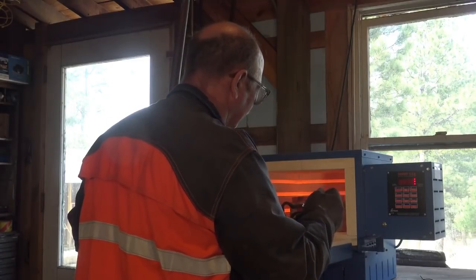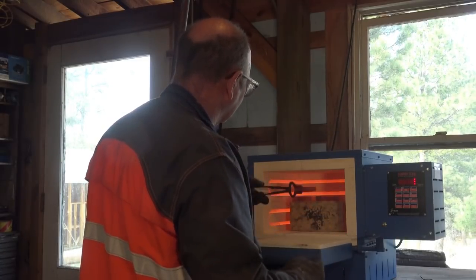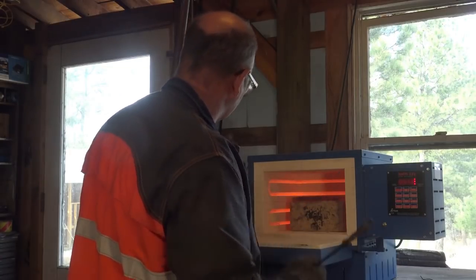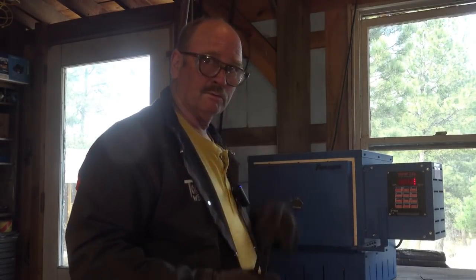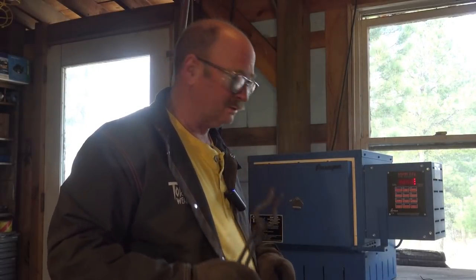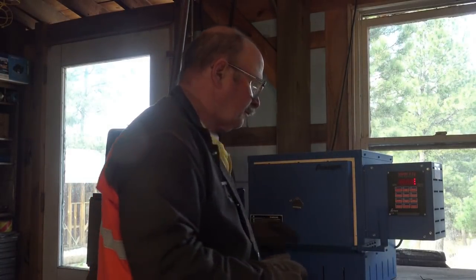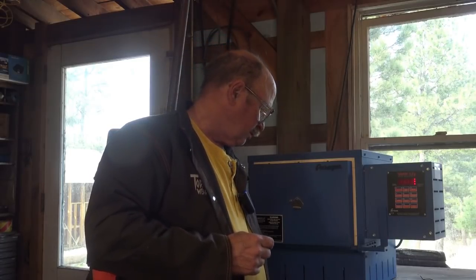It depends on where you test it. The part that's sitting up on this brick must still be a little bit cooler because it's magnetic. The part hanging over the back end is not magnetic. That's a very interesting finding right there. But I think that means that our part that's fully exposed to the atmosphere inside the heat treat furnace is at the correct temperature, and the part over the brick perhaps is not. So 4140 should have a critical temperature of 1570, and at 1475 we're clearly losing the magnetism, so that's 100 degrees below critical temperature.